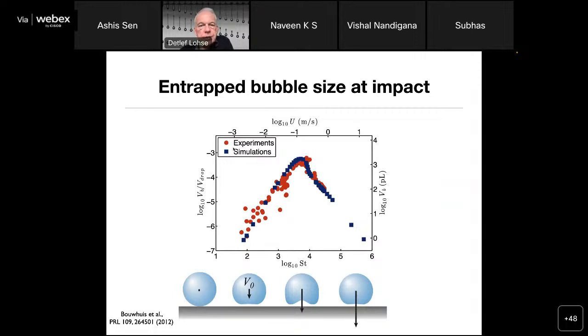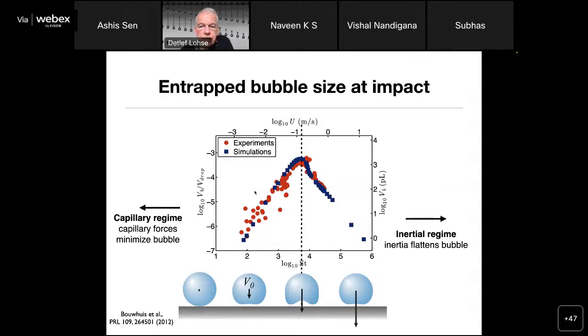So red is experiment and blue is simulations, and we have two regimes. We have a capillary regime on the left, and we have an inertial regime. So when you very gently deposit the droplet on the substrate, you don't get much deformation, and the entrained bubble is very, very small. And on the right, you are in the inertial regime. There you smash the droplet against the surface, and also there you don't get much of an entrained bubble. But in between, you have a maximum. And look how pronounced it is. You can also calculate the scaling laws here and here simply by balancing the forces.